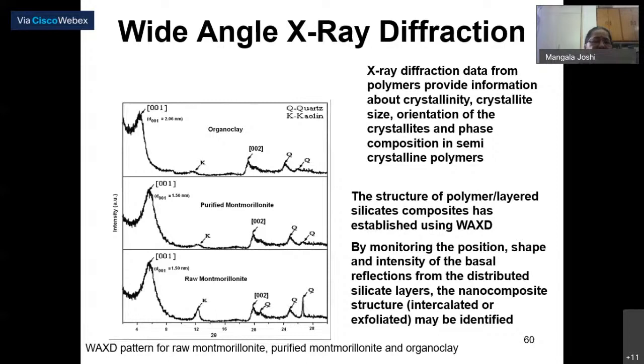Here what we are doing is we have mixed polymer with a clay. Now clay is a high modulus material compared to polymer, and we are putting the clay in the polymer. The clay is supposed to disperse and exfoliate. So if you run an X-ray and the clay is still in stacks, then you can see a very clear peak. Put it in the polymer and you see a very small peak because you have added very little amount. But if you see a very distinct peak, that means your clay has not dispersed in the polymer.